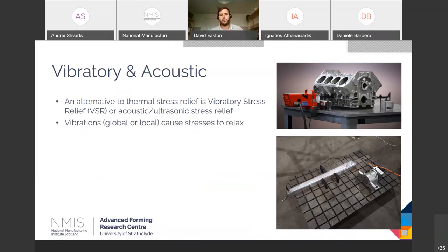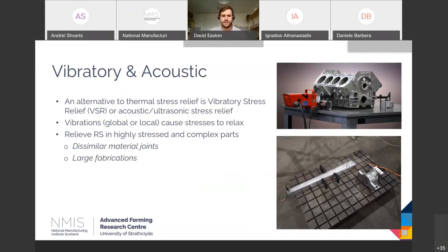Here we are basically vibrating a part either globally in the case of vibratory stress relief, or locally in the case of acoustic or ultrasonic stress relief. And this causes dislocation movement, which causes a relaxation in residual stress. So this is particularly useful for large parts, heavy parts, dissimilar material joints, large fabrications, additive manufactured parts, and we avoid the problems that can be associated with heat treatment.